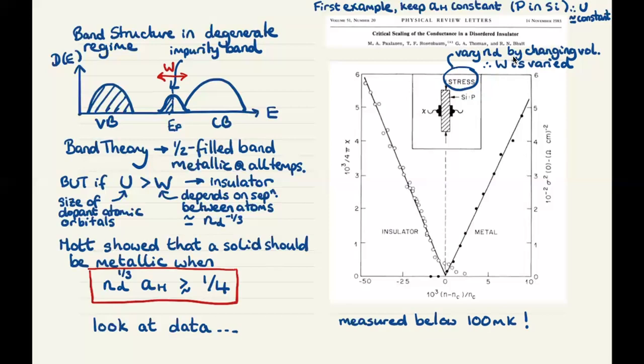So let's look at what we're looking at here. On the left-hand y-axis is plotted 1 over the dielectric susceptibility. And the dielectric susceptibility diverges in a metal. And so as 1 over the dielectric susceptibility approaches 0, that's an indicator of approaching the metal insulator transition. So these dots here are measures of the reciprocal dielectric susceptibility in the insulating regime. And we see that as the atoms are moved closer together, the system starts to approach becoming metallic. So as we've moved down in this direction, the atoms are pushed closer together. 1 over the dielectric susceptibility is going down towards zero. The susceptibility is diverging, so the system is moving towards being a metal.